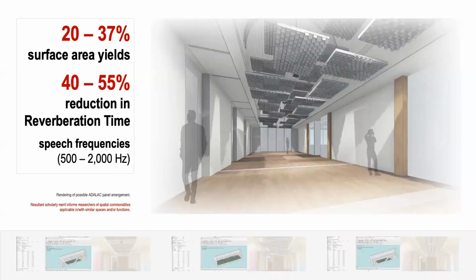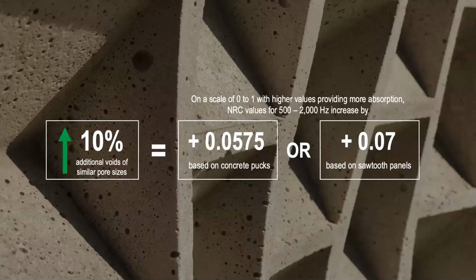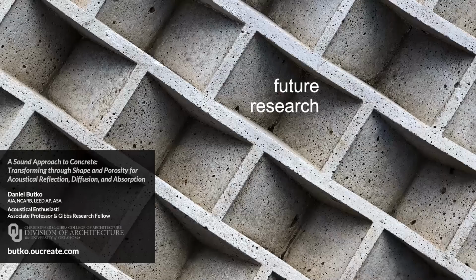The compiled data indicates replacing 20 to 37% of a room's surface area with the aerated faceted concrete panels, or suspended in the space, will yield a 40 to 55% reduction in RT at speech frequencies. Data collected on the various concrete pucks and subsequent calculations suggest for every additional 10% of voids per volume, the average NRC values focused on speech frequencies increased by 0.0575 within the concrete mix. When accounting for the panels and sawtooth facets, the total NRC increase is approximately 0.07 per the same 10% voids, with noted heightened absorption in specific frequencies due to panel orientation.